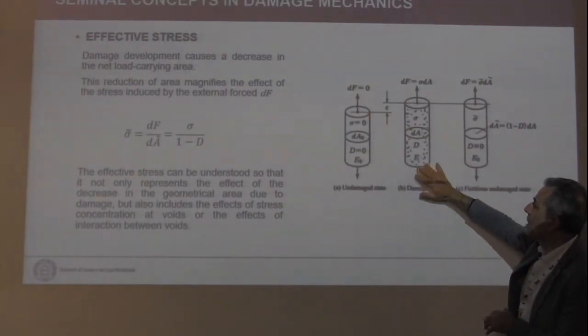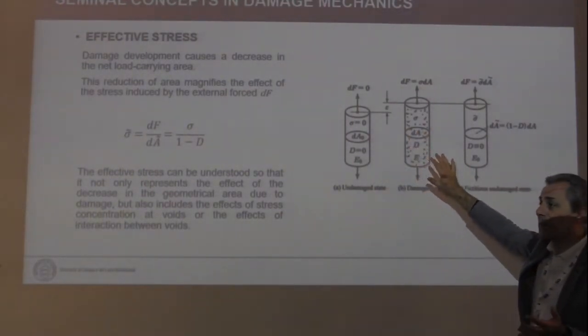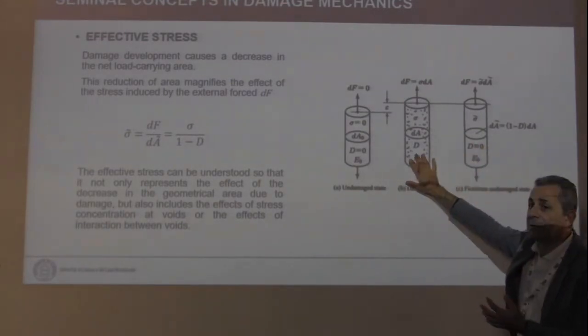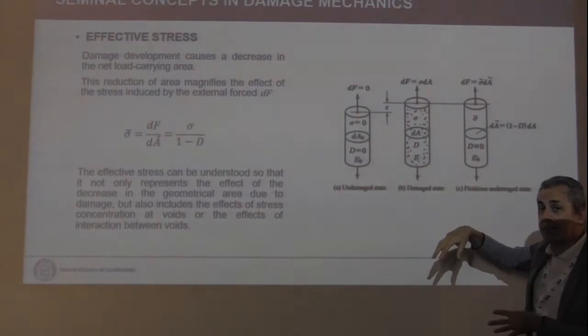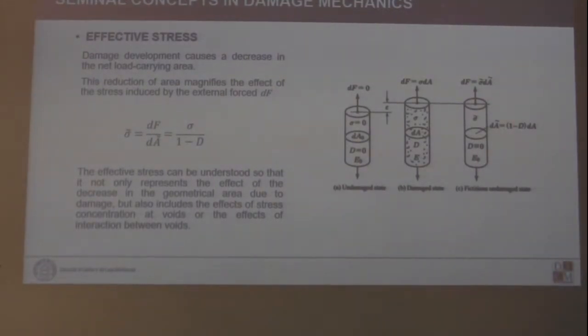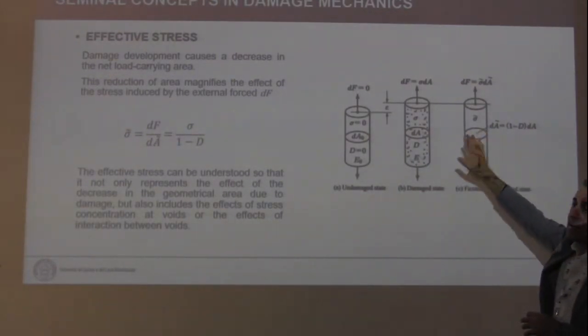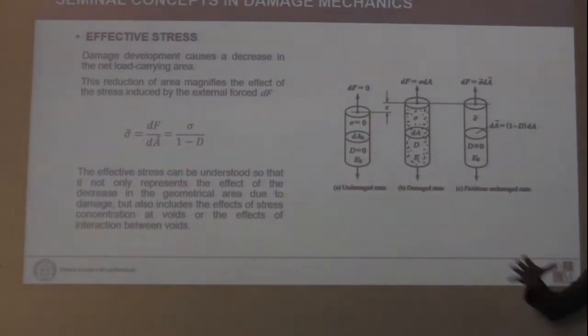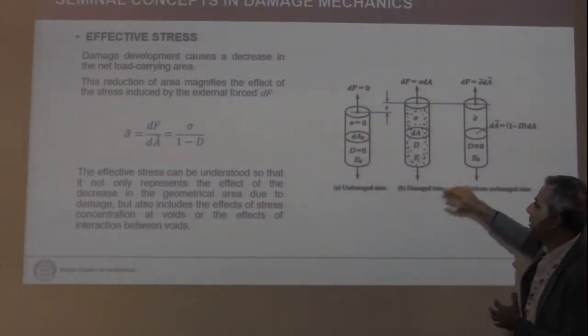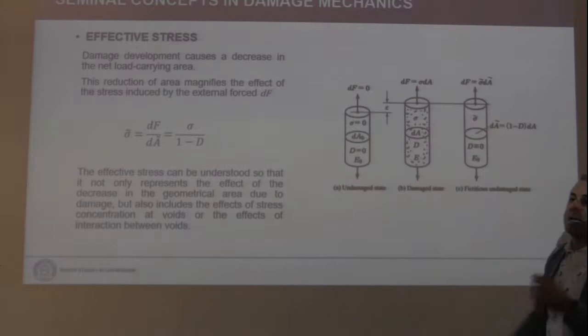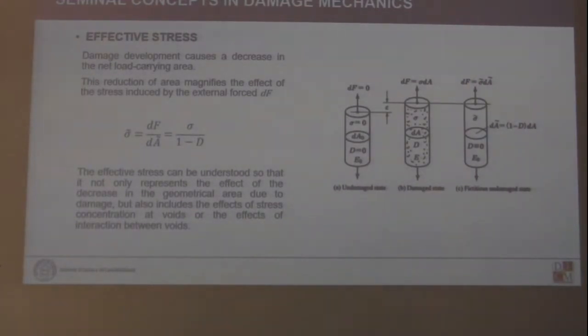But instead of dealing with this very complex problem, we can deal with a virtual material that has no damage but has some degraded properties. This is a turning point, and in this equivalent material, the stress is no longer sigma but a higher stress, which accounts not only for the reduction of the area but also for the concentration of stresses. So, in doing this, we have the possibility to get rid of the peculiarity of each damage form, shape, and evolution in the material, and just capture, outside the boundary of our body, what the detrimental effect is.